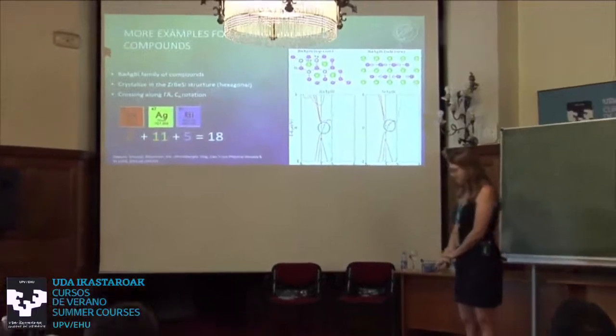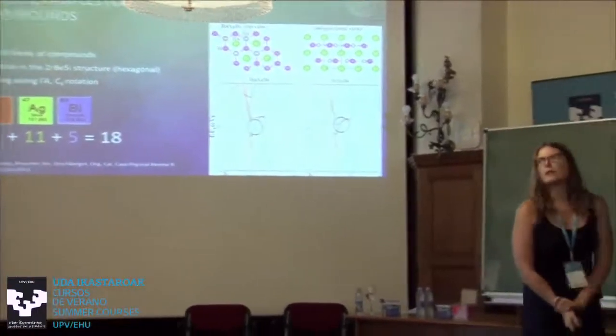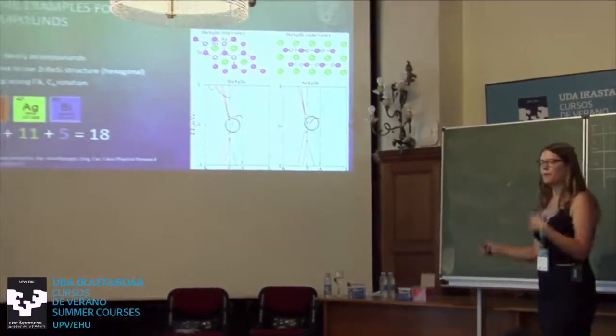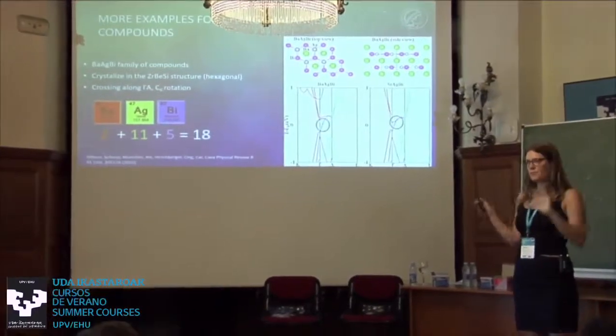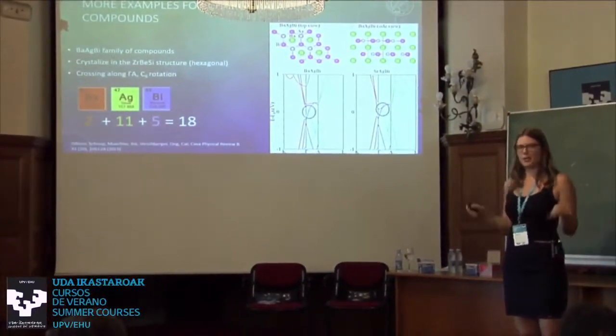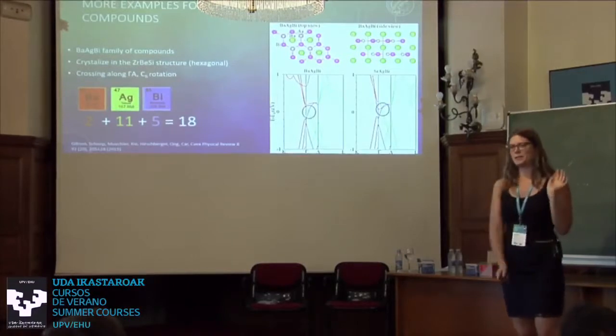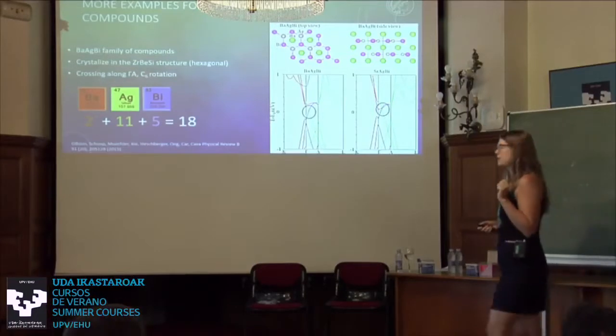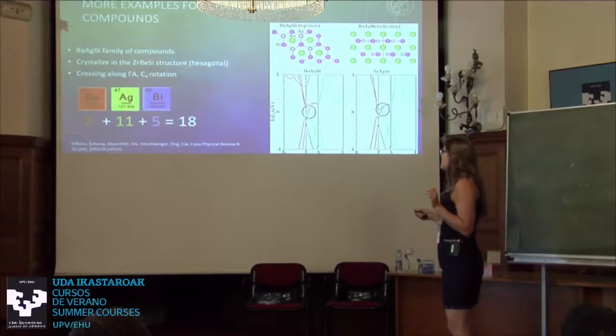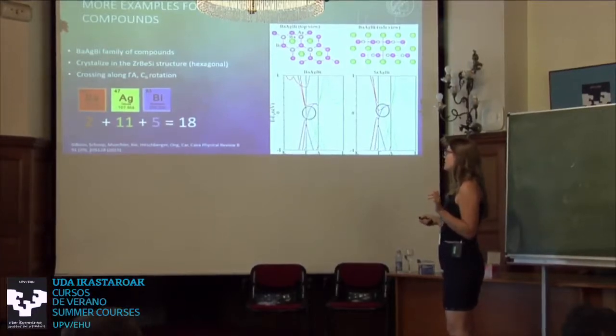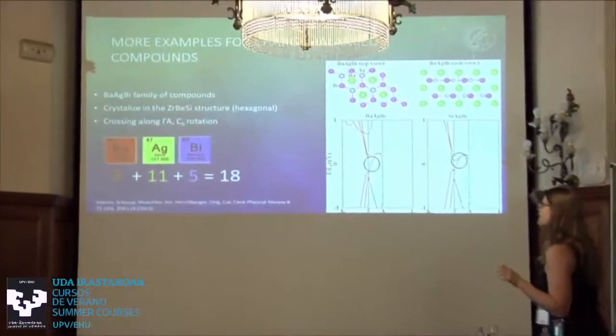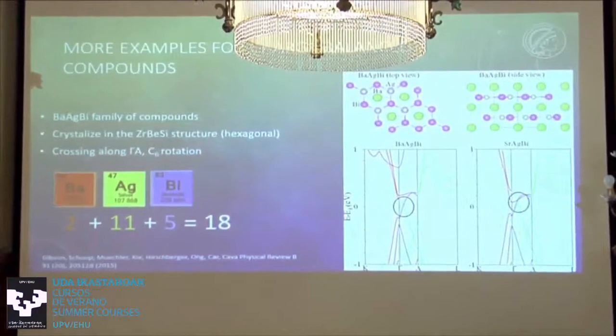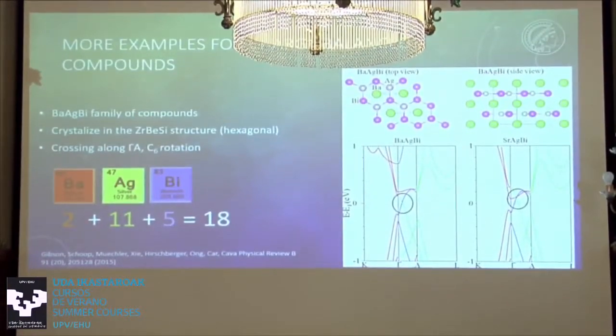So that's why at some point, Quinn Gibson, who was also a grad student at Princeton with me, and I wanted to somehow get a better feeling for it and try to quantify this spin-orbit coupling versus electronegativity difference enigma, to get an idea when this is actually good for having a clean 3D Dirac semimetal. And so for this, we started to look at this barium, silver, bismuth family of compounds. So barium, silver, bismuth is shown here. It has 18 electrons, and you can substitute the elements isoelectronically, and you stay in the same structure type. So those have hexagonal structures, and they can have band crossings along the gamma A line where the 6/3 symmetry is. But you see here, for example, already that barium, silver, bismuth is a very nice and clean 3D Dirac semimetal.